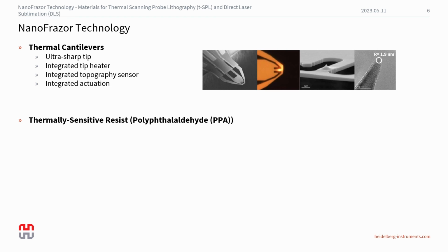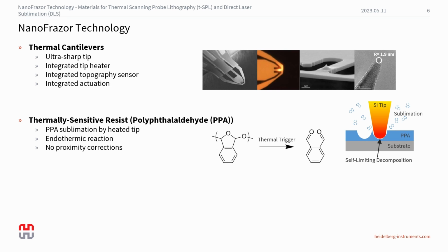The second aspect that really starts to unlock the nanofabrication capabilities of t-SPL is using a thermally sensitive resist, specifically polyphthalaldehyde or PPA. So this material has quite a few unique characteristics to it, and we'll go into all of these topics in detail in the coming slides. But briefly, PPA is able to be directly sublimated with the hot tip, and this allows for the polymer to go straight from a solid phase into a gas phase locally under the heated tip. It's also an endothermic reaction, this depolymerization, so it is not spreading any heat with respect to this reaction.